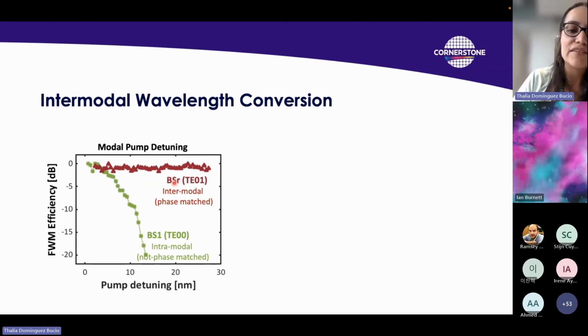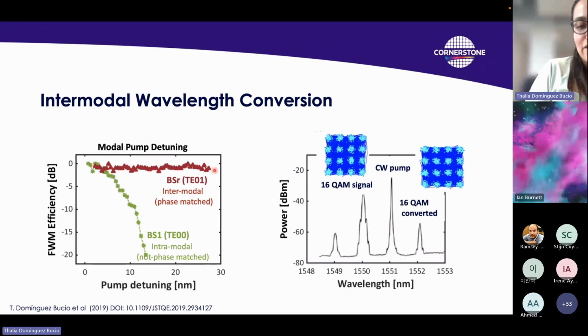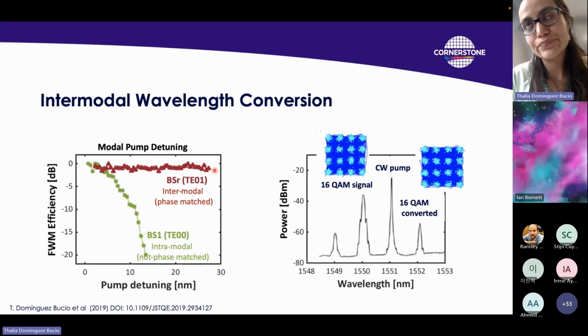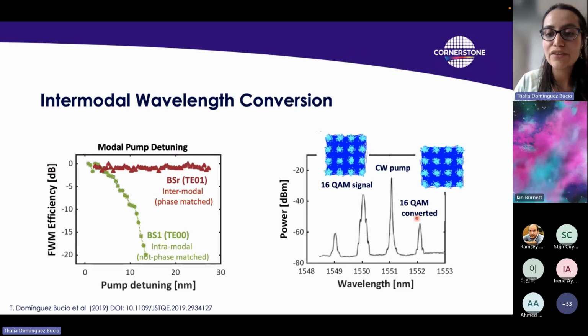Whereas when we have this intermodal process, we see that even if we tune the pump up to 30 nanometers, the process is still phase matched. So that means that we can move our generated idler to much longer wavelengths. And by using this kind of scheme, it is possible to demonstrate modulated signals, like quadrature amplitude modulated signals, that start at 1550 nanometers, and then they are converted in our nonlinear waveguide to longer wavelengths, all the way to 1600 nanometers.